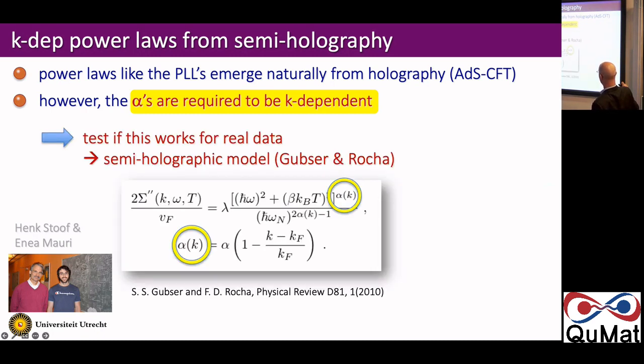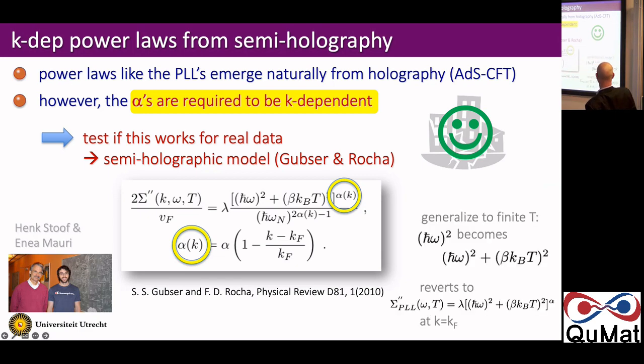So Inea and Henk chose this Gubser and Rocha model, a semi-holographic model, which can be solved both analytically but also numerically. And you have this kind of formula coming out from that model, where you'd have your h bar omega squared plus beta kB T squared to some power alpha, but alpha is a function of k in the sense that it's 1 minus k minus kF over kF. So when k is equal to kF, alpha is just alpha, and as you go away from kF, this alpha is in fact changing. So we can rhyme everything again, but with a very important message coming out.